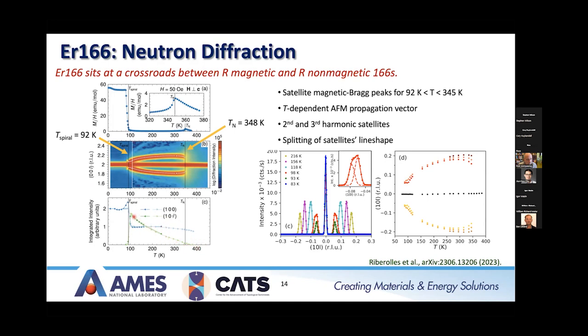So that's the green intensity growing with decreasing temperature. They suddenly disappear. And at the same time, for this 100 structural Bragg peak, there is no real change above T-spiral, but below T-spiral you get this sudden jump in intensity.